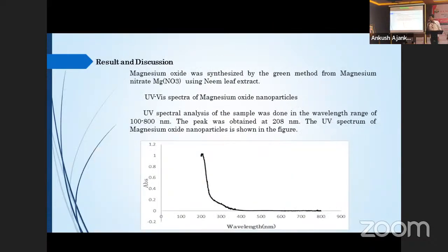Result and discussion. Magnesium oxide was synthesized by the green method from magnesium nitrate using neem leaves extract. So this is the absorption and this is the wavelength. The UV spectral analysis of the sample was done in the wavelength range of 100 to 800 nanometers, and the highest peak is at 208 nanometers.